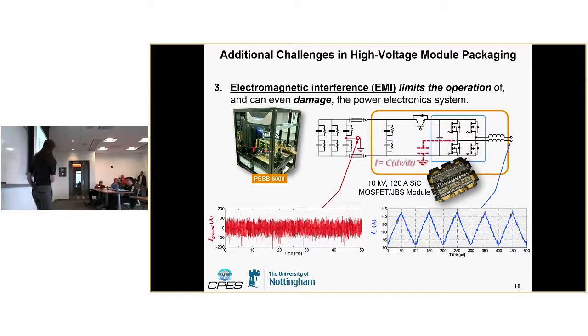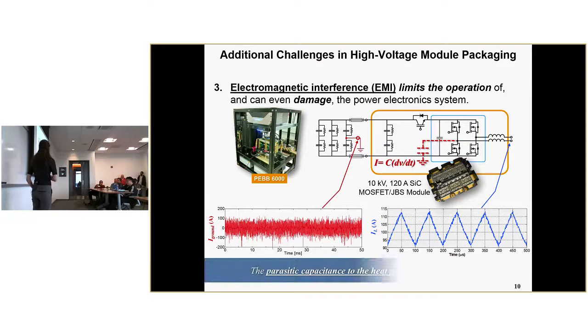And part of the reason is that this power module package was designed for silicon IGBTs that switch more than an order of magnitude slower than these silicon carbide MOSFETs. So now you've got the same amount of capacitance for much higher dv/dt. So now you can get more than tens of amps of current flowing through this parasitic capacitance to your heatsink, which is grounded for safety purposes. And then that will couple through your control circuitry. So that's also something that needs to be considered.